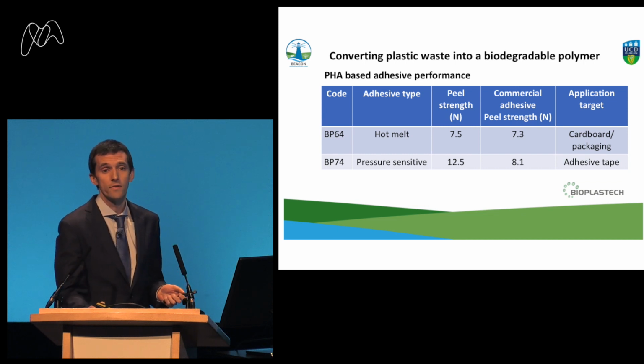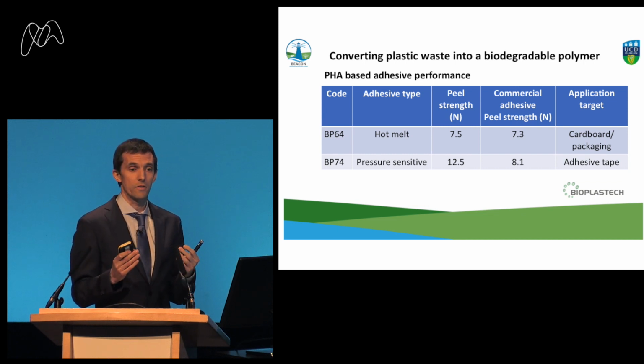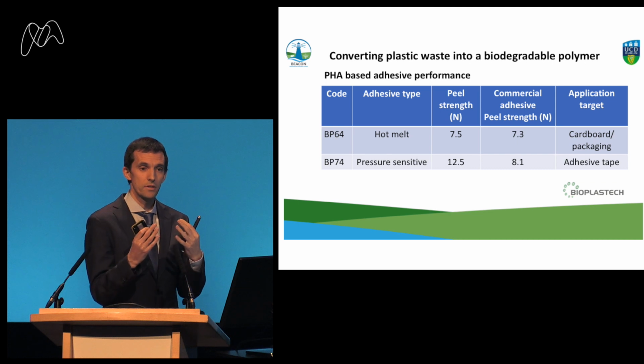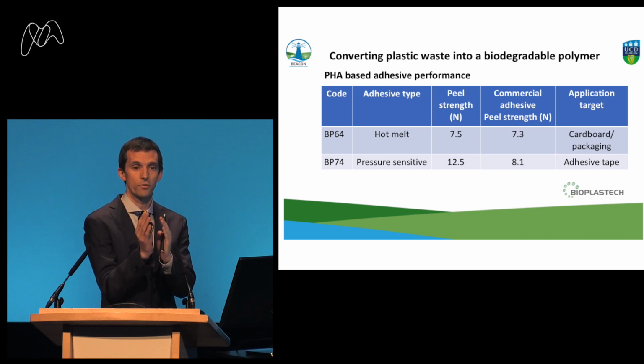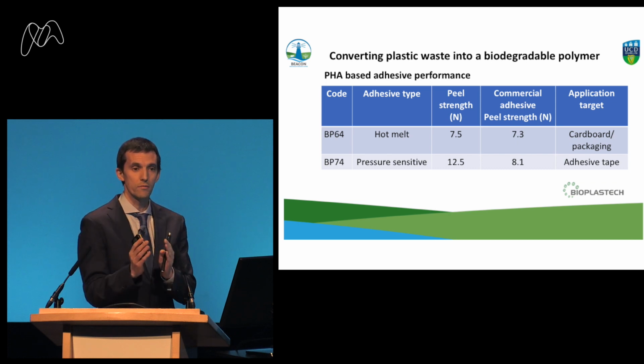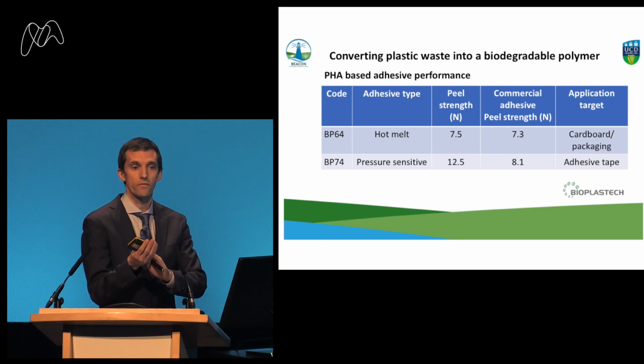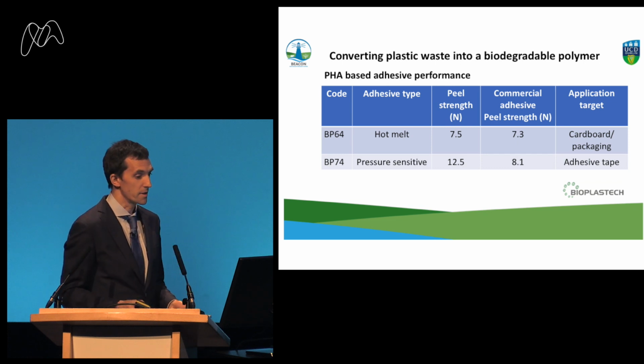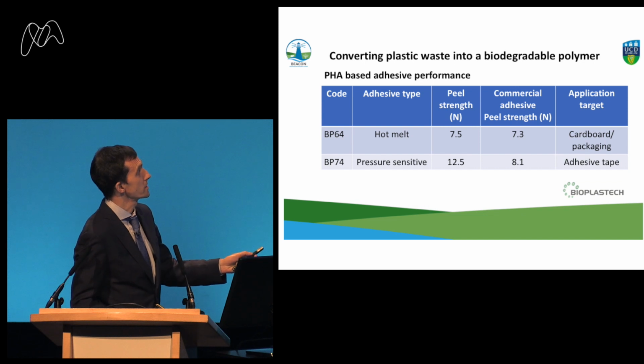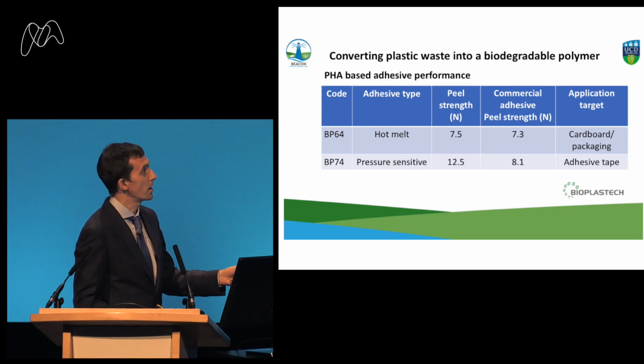A hot melt adhesive is effectively an adhesive or a polymer that you heat up. It becomes liquid. You then take two surfaces and put them together. The liquid cools down and then bonds both surfaces together. And that's a hot melt adhesive. Our hot melt adhesive has a peel strength of about 7.5 newtons. And compared to the commercial adhesive, it's exactly the same. And we can use that for cardboard and packaging bonding.